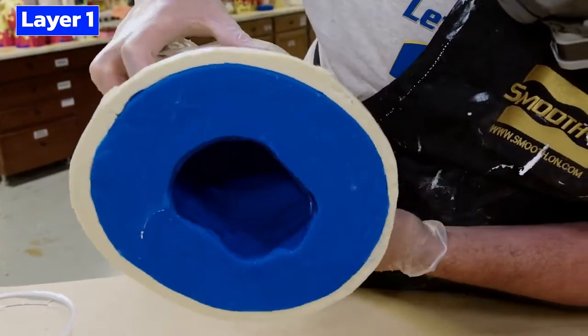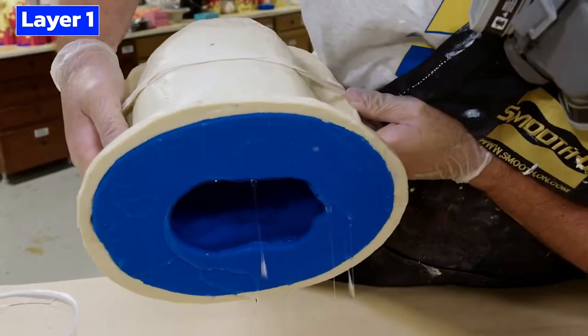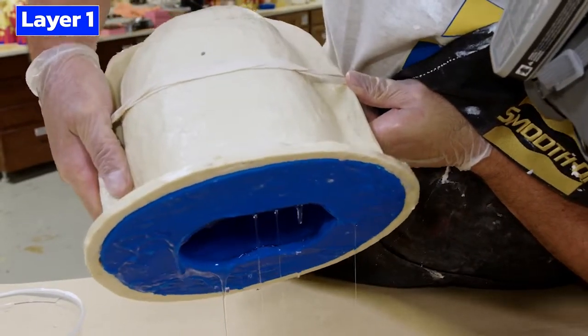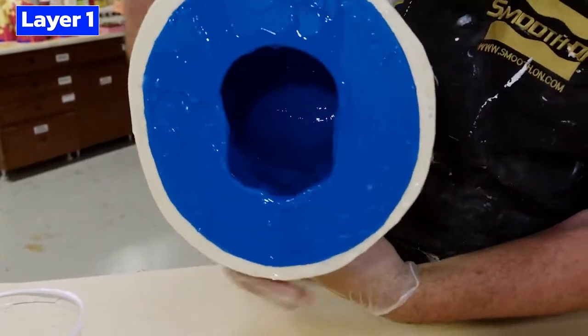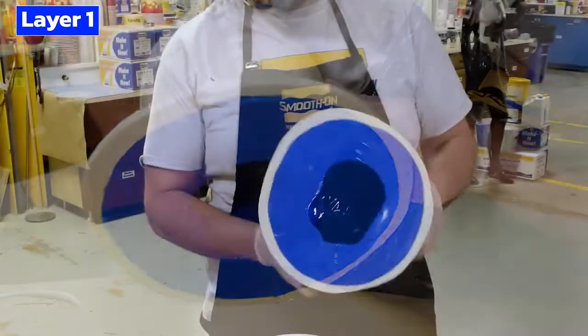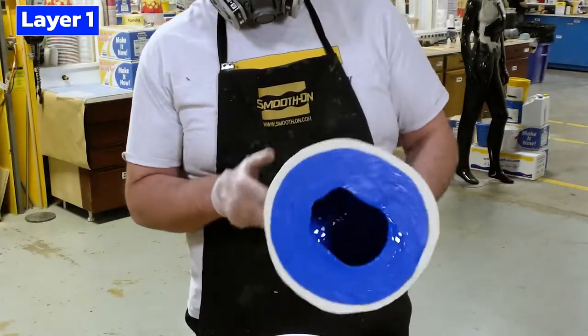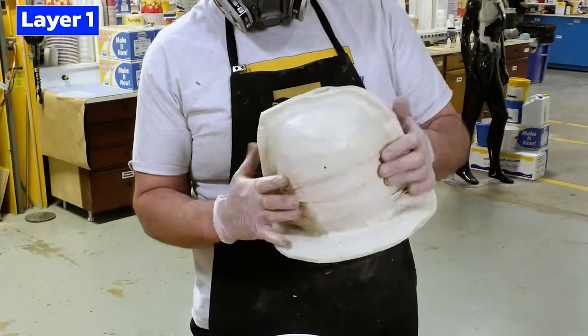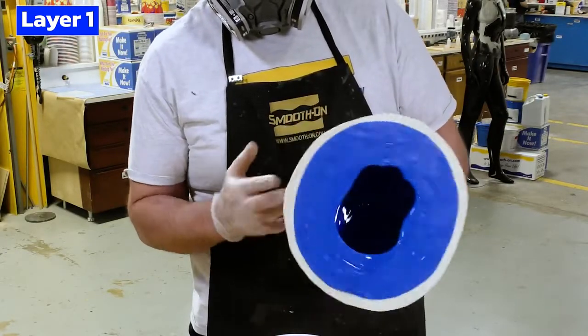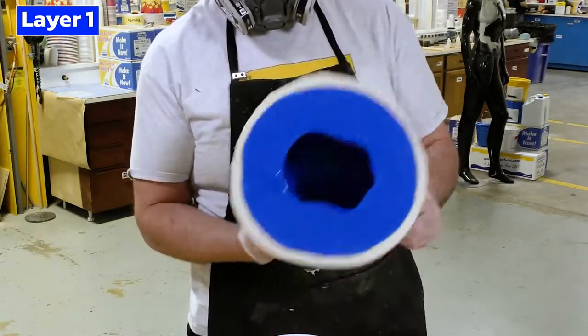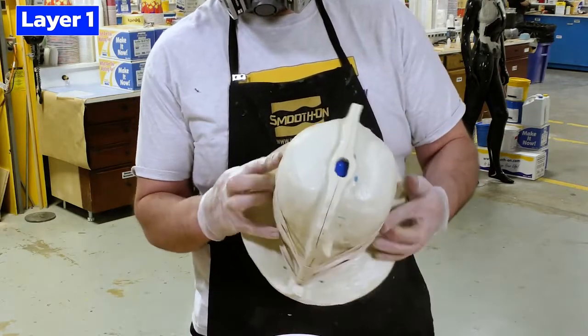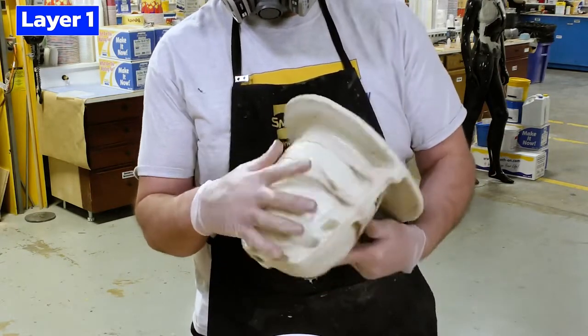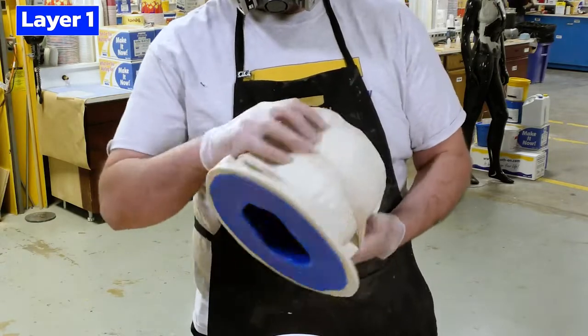As you have noticed, I'm not catching any of the extra resin that we're spilling over the edge of our mold and trying to put it back inside the mold. If we were to catch the resin and then pour it back into our mold, in that process, there's going to be a lot of air bubbles introduced to that material that are going to end up in the casting itself. And to minimize that possibility, we're not going to use that extra material.